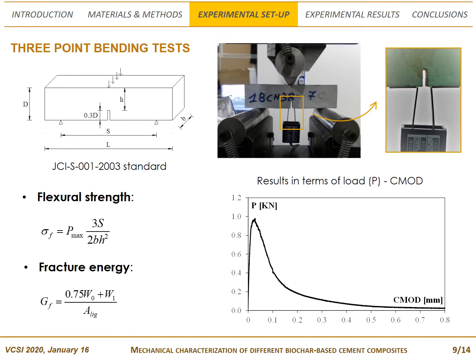The prismatic notched specimen was subjected to 3-point bending tests under crack mouth opening displacement control in order to evaluate both flexural strength and fracture energy. Fracture energy was evaluated by using the equation proposed in the Japanese standard, by integrating the area below the load-CMOD curve and taking into account the work done by the dead weight of the specimen and the loading equipment.